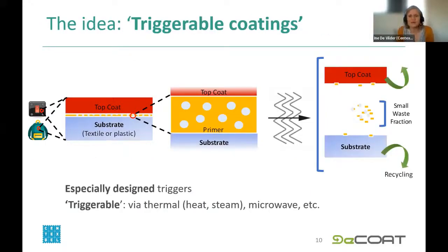So here you have a schematic overview of the principle of the triggerable coating. Between the substrate and the top coats, we have a primer or an adhesive layer where we will put specially designed triggers. During the use phase, these triggers are just there doing nothing, so to speak. And at the end of life, these triggers will be activated. This can be done thermally via heat or steam, or via microwave. When we trigger, they induce the separation of the substrate and the top coat. And thus this substrate can go back to recycling.